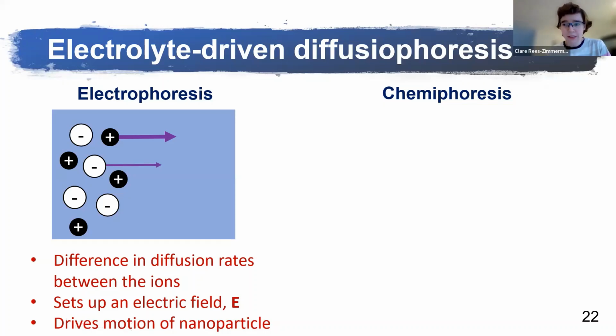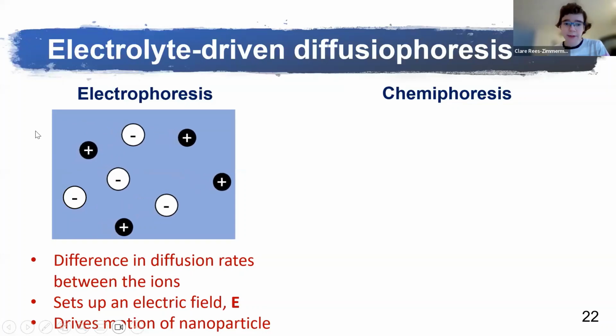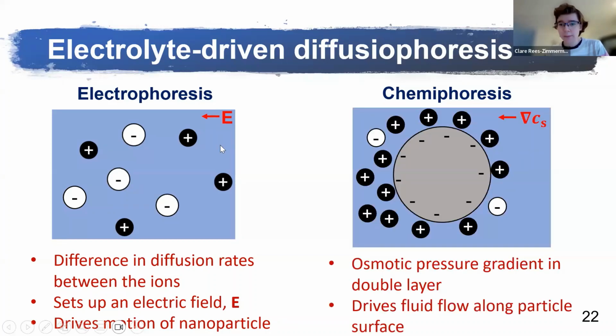Because they're different sizes, they diffuse at different rates. This in turn sets up an electric field between our cations and our anions, and this electric field can drive the motion of a nanoparticle with a surface charge. Chemiphoresis occurs because the concentration gradient of ions also means that there's an osmotic pressure gradient around each nanoparticle. This osmotic pressure gradient drives fluid flow along the particle surface and in turn drives the particle up the concentration gradient of the ions.